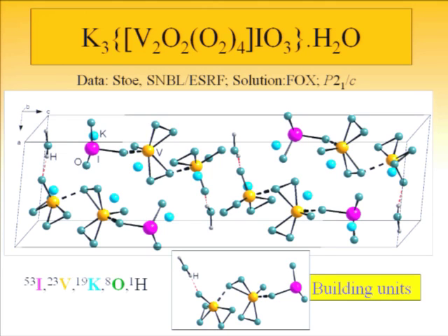And here's the building unit, vanadium. This is peroxide here, one oxygen at a longer distance. And finally, this is the sixth one from iodate. Here you can find 1, 2, 3, 4, 5. And the sixth, this is the sixth oxygen coordinating the vanadium atom, and one tiny hydrogen bond from the water present in the structure.